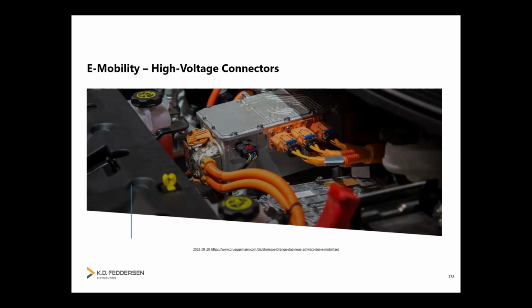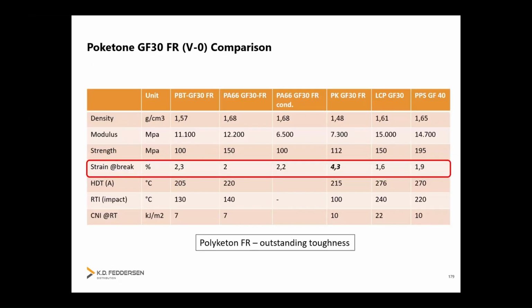for me, polyketone is the superior material because it has significantly higher toughness than all the other materials that are used. I've made a comparison with the strain at break. You can see various materials that are listed, so not only these two materials that are used, but I've also added a few others for comparison, and you can see that the margin the material gives, after the glass fiber and flame retardancy, is that you have twice as much elongation at break. And typically, when material is aging over time with heat and time, the material and parts typically break due to brittleness. And here you have a huge safety margin in terms of long-term application as well as for all the clips. So it's twice as much as every other material.